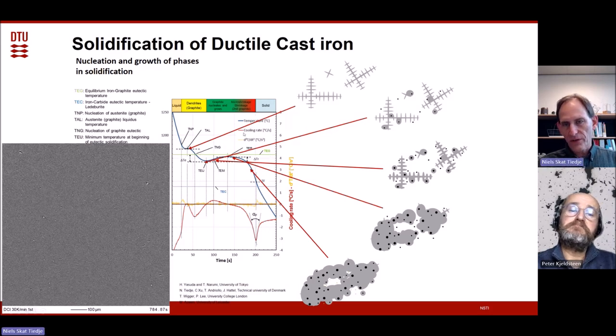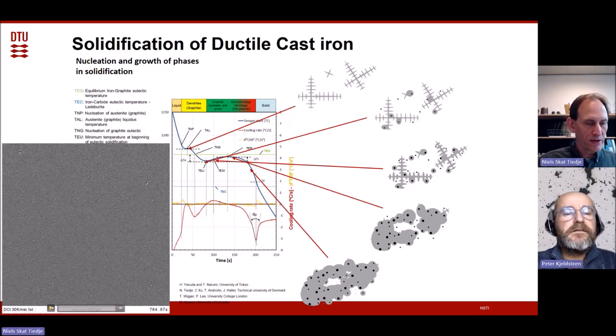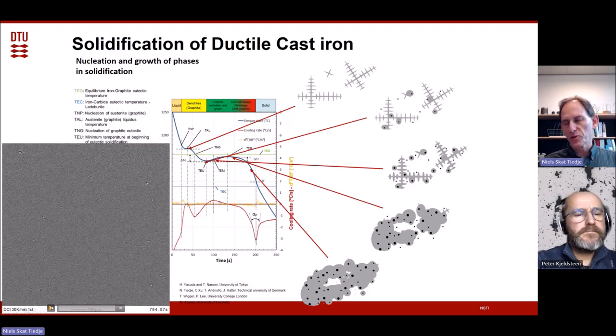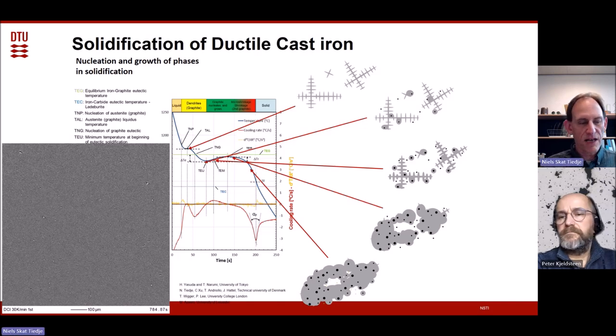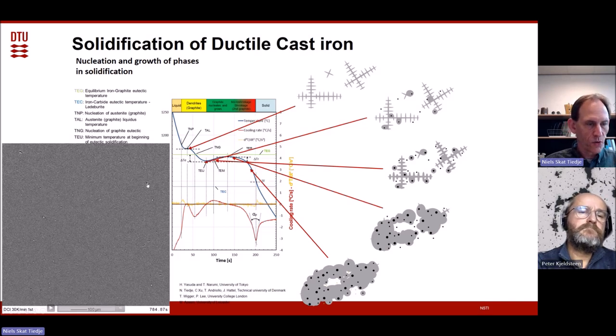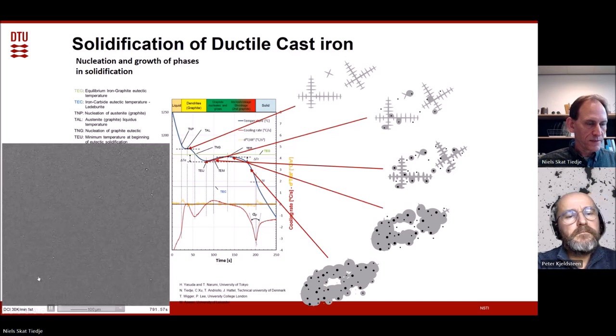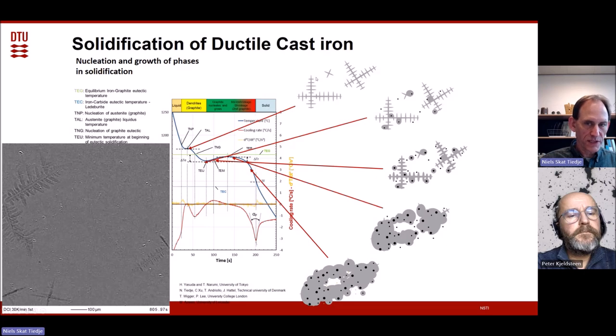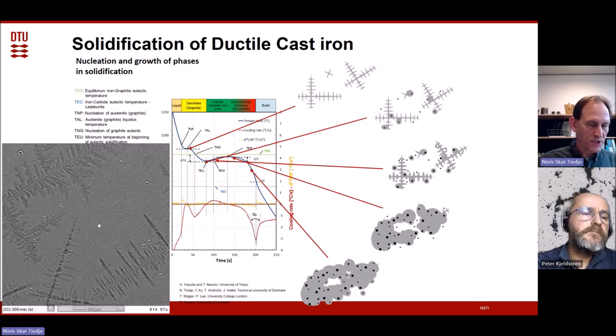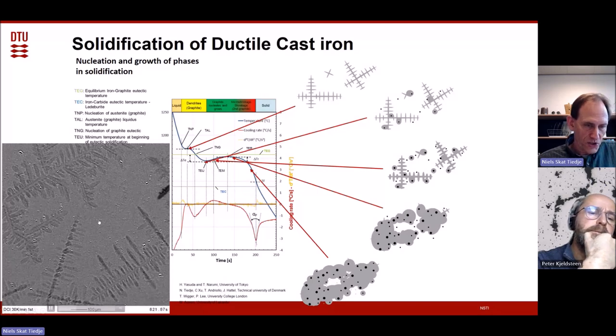But what is sketched on the graph here, we did with some Japanese friends that have the expertise to make 2D X-ray videos. In this case, we're looking at a 200 micron thick cast iron sample, and we're looking in two dimensions through it. What we see here is liquid. There's a lot of noise, some white dots and stuff. But then we see in a minute dendrites, the first austenite, what we see on the right on the graph. And then we will see very shortly white dots, which is the graphite.